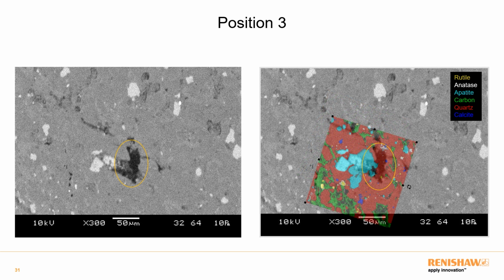Lastly, I'm going to look at position 3, and here I want to highlight some of the variation between the two techniques. Again, we've picked a region here which is primarily carbon and quartz. In the SEM image, we have this black region, and we thought, okay, what is this? Maybe we can find out from the Raman. Well, what we see from the Raman is not very much. It still matches this quartz, and it probably suggests that it's not different. This could be an artifact from the SEM image, or it could be some surface contamination.